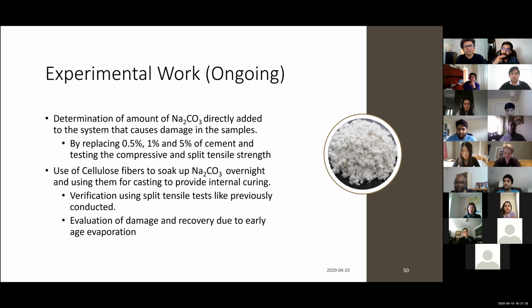We started at a small amount. I think, Anupam, how many percent? Okay, 0.5%. 0.5% is what we started off with. That brings in about, I think, 72 grams of sodium carbonate. Yeah, that's a lot. The problem is we are thinking let's start small, gradually scale up until we hit the plateau where the sodium carbonate does not affect your strength anymore. The thinking is, if we gradually scale up, bringing small dosages to the point where we don't see any drop in strength, hopefully at that point the self-healing can take place.